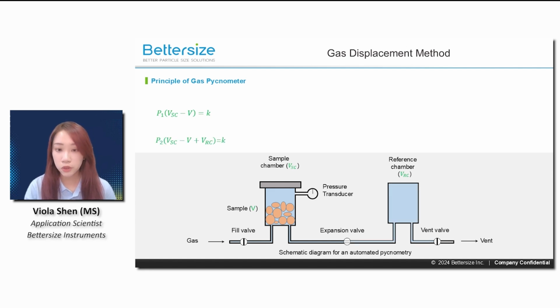Next, we open the expansion valve, allowing the gas to flow from the sample chamber to the reference chamber. And once the equilibrium is reached, the pressure is measured as P2, and we have another formula. Using Boyle's law and the known volumes of the sample chamber and the reference chamber, along with the recorded values of P1 and P2, the volume of the sample can be calculated by the software, with the sample's mass easily obtained by a precise balance. We can then determine the true density.